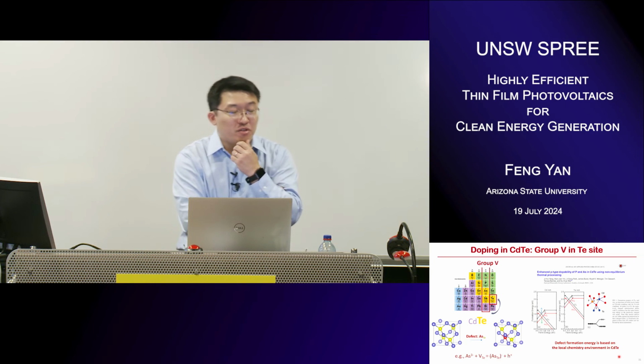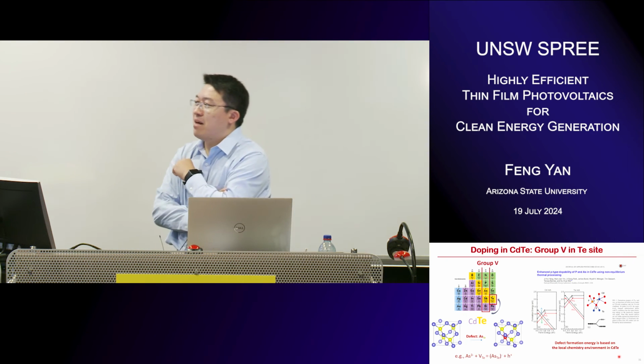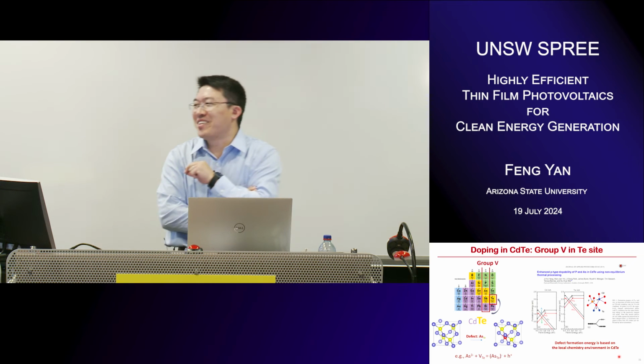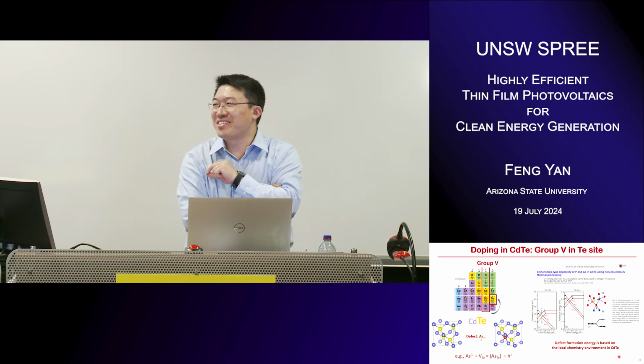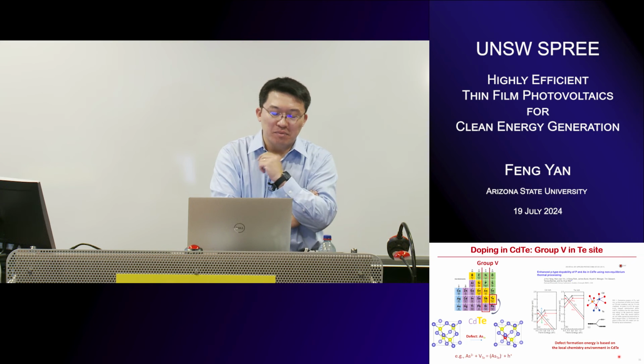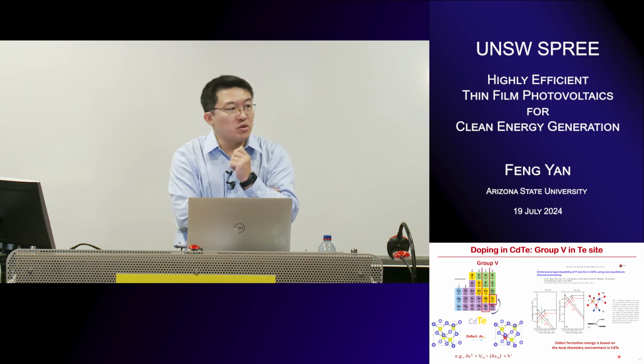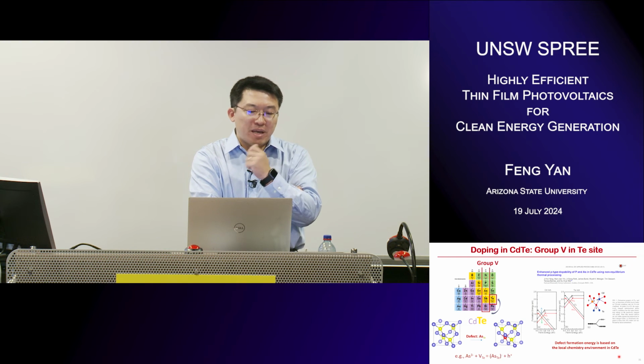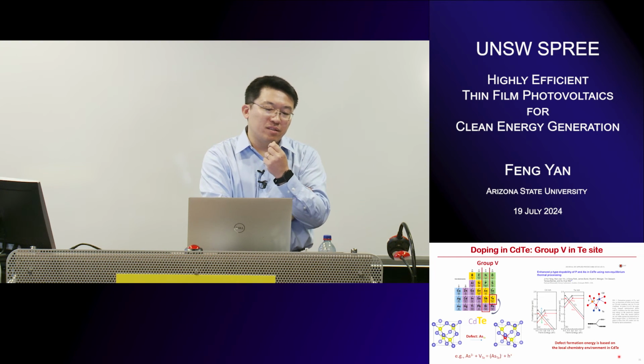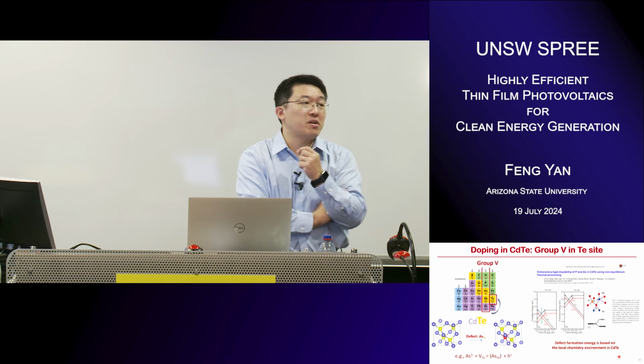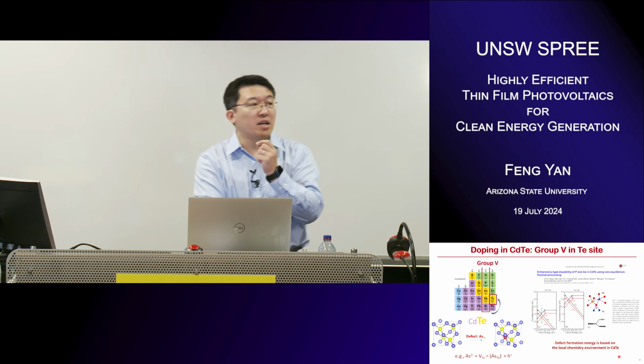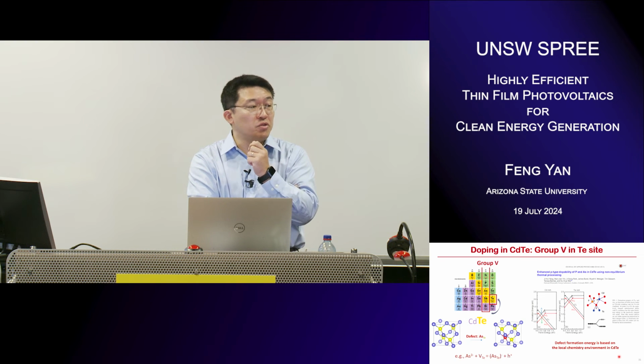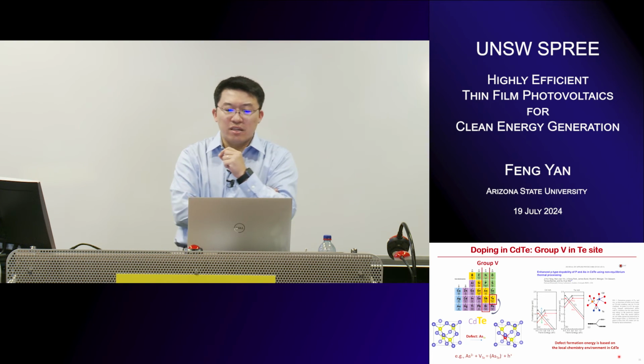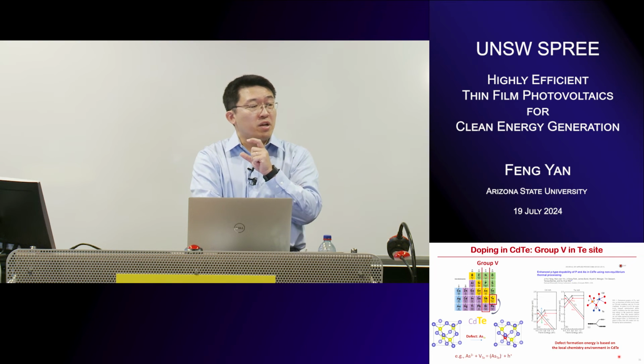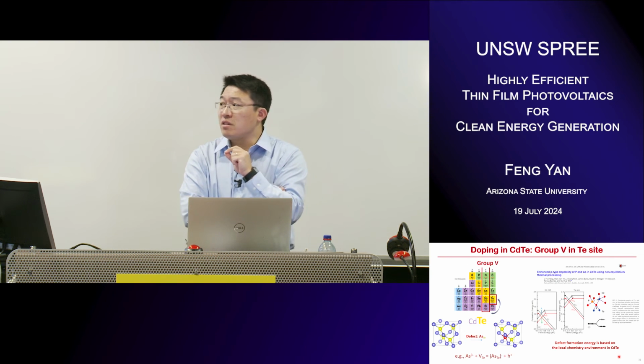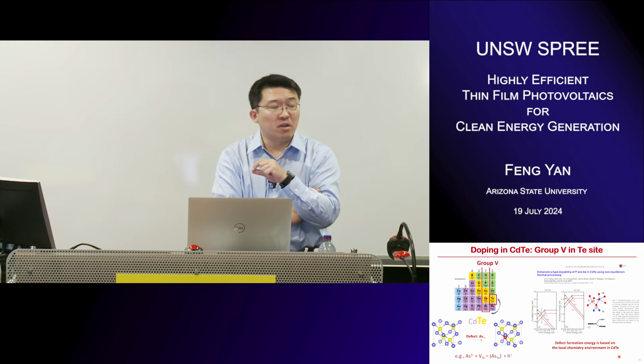Going back to the first question, which element we try: we try all of them. We play with 20 or 30 chemicals. To be honest, this is the advantage of working in the lab. For the second question, which one is desired? Based on my understanding, probably phosphorus and arsenic are easier to introduce because they have a relatively smaller ionic radius and higher diffusivity in the device. Antimony and bismuth have a relatively large ionic radius and are heavy, so it's difficult to drive them in. Particularly, we prefer a low temperature.